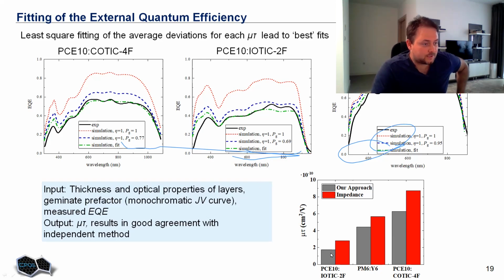So in this case, you can see we determine this mu tau product for 3 systems. These are the gray bars. They define the value of this mu tau product. And we also performed a way more complicated analysis, which implies application of voltage dependent, bias dependent impedance spectroscopy, in order to determine this mu tau product with an independent method in the same devices. You can see it's a very nice trend. There is obviously some discrepancy in values, but it's not much, and the trend is really good.